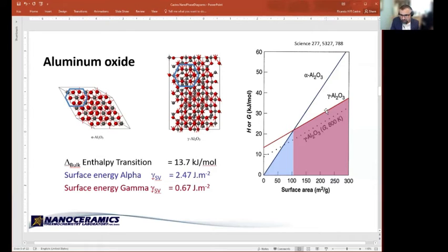What do you mean? You're saying that the polymorph stability changes at the nanoscale? So is this phase more stable? Well, the correct terminology would be metastable, right? This is a metastable phase compared to alpha alumina, because the surface is actually stabilizing it, as compared to the same surface area of alpha.